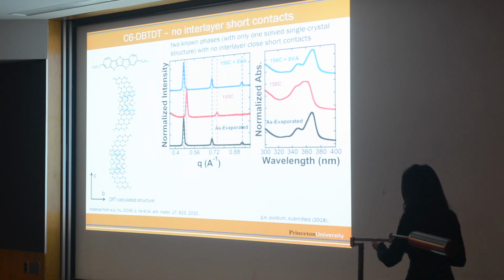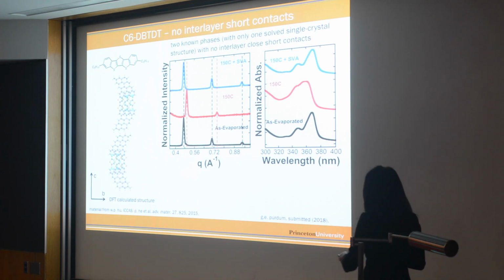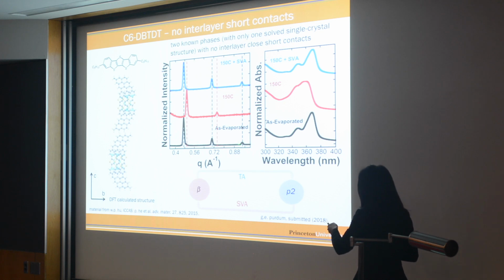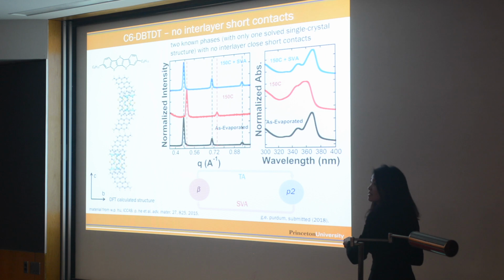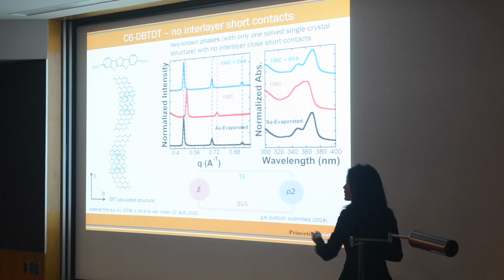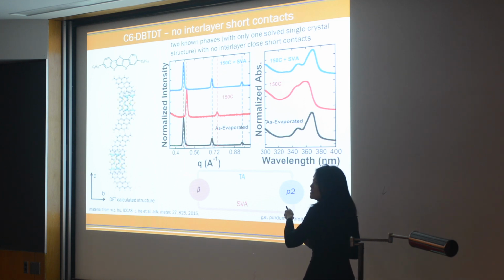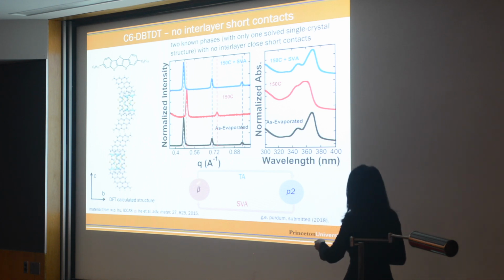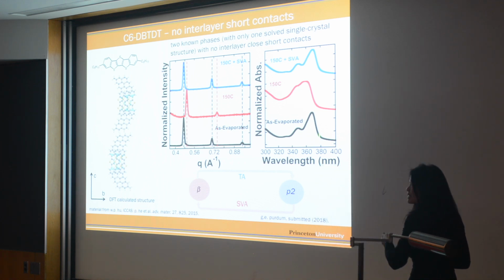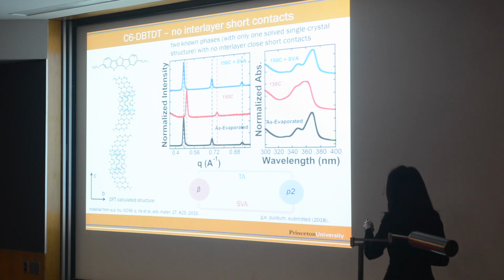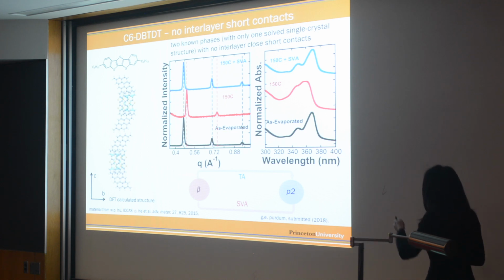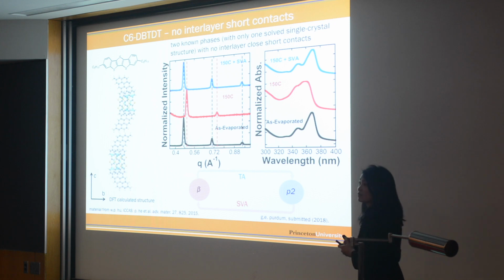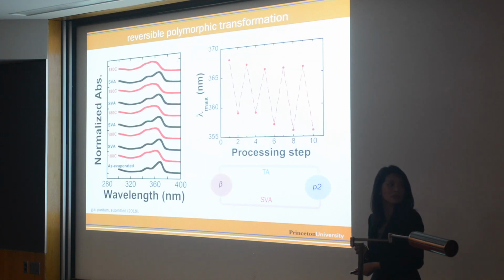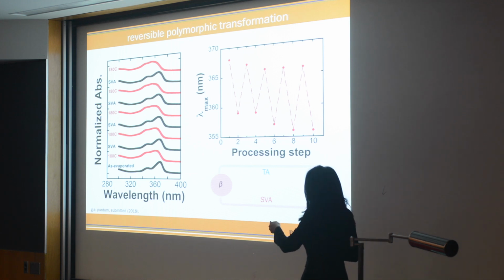And so this is the data. This is X-ray diffraction as well as UV-vis absorption data. As evaporated, we access a beta phase. And then we can thermally anneal it, and that pushes us to P2. We call it P2 because we don't know the crystal structure, but we know it's a different crystal structure from the beta phase. And then if we solvent vapor anneal it, we get back to the beta phase. So this is the processing map. You can see this also by the fingerprinting in the UV-vis data. As evaporated, we have a red-shifted lambda max, and then we blue shift it when we thermally anneal it, and then we shift it back in the red when we solvent vapor anneal it. And we can go back and forth. So this is a series that shows that we can go back and forth, back and forth.